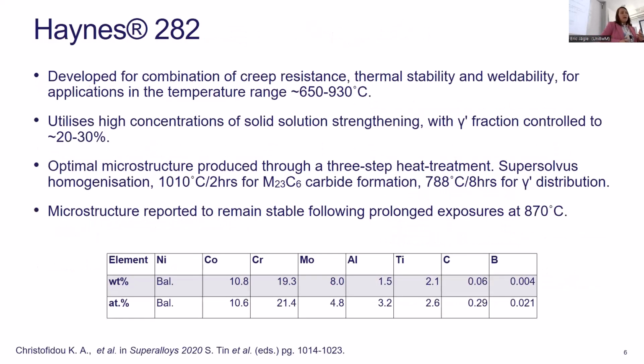So there's a lot of challenges still, and the more materials we look at, the more challenging it gets. So in this particular work, we were looking at Haynes 282. This was an alloy that was developed for a combination of good creep resistance, thermal stability, and weldability for applications in a range of temperatures from 650 to about 930. And one of the reasons that we were interested in Haynes 282 is that it has a fairly large range of temperature capabilities at a fairly controlled and low fraction of gamma prime. So our gamma prime fraction is controlled to about 20 to 30%, and the microstructure is optimized through heat treatment.